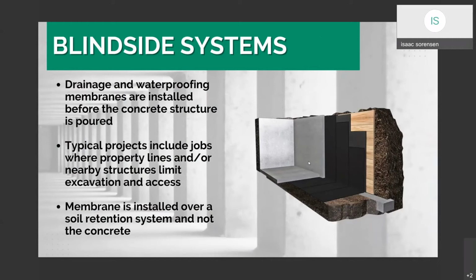One of the most important things about placing a blindside system is making sure that the manufacturer's installation instructions are followed. Very importantly, the adherence to the top of the lagging becomes a real issue. One of the things we see out in the field is the failure of blindside systems when they are literally dragged down the wall while the concrete is being poured, because the adherence to the top of the lagging wasn't correct. So if we can place a termination bar, just make sure that it's properly adhered, so that when the weight of the concrete is poured into the forms, the material itself will not be dragged off of the substrate.